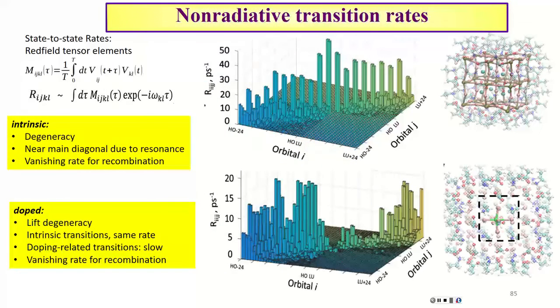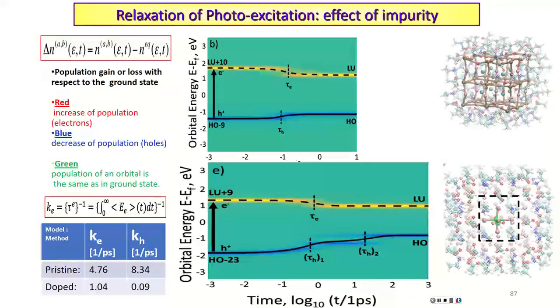And as time passes by, these couplings between states allow the change of the energy of the electron and hole versus time. As time passes by, the electron floats to lower energy and the hole floats up to higher energy. In the presence of spin orbit, the relaxation in this work by Aaron is found to be slower because spin orbit brings additional splitting, additional subgaps. This result of Aaron is controversial to a recent publication of Alexey Akimov, who claims that the presence of spin orbit increases couplings and makes relaxation quicker. So debates are to come.